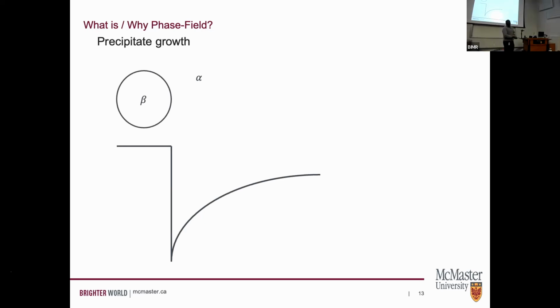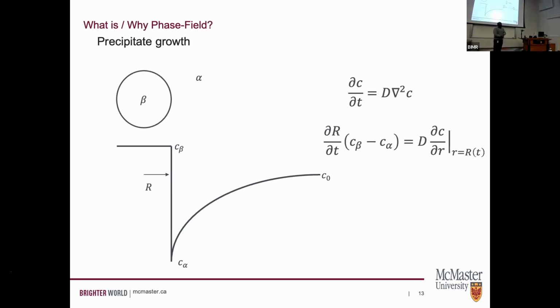And I want to know two things: how this phase beta is going to grow and what's going to happen with the composition. It's a problem from like the 20s or 30s by a fellow named Zener. The conditions of my problem are the beta phase is at its equilibrium concentration, and then some far away, I have this average concentration C naught. This is the only equation I have. It drives mass transfer. But at the interface, I need to apply this boundary condition.